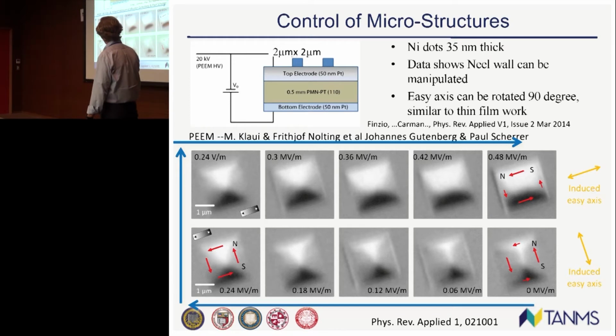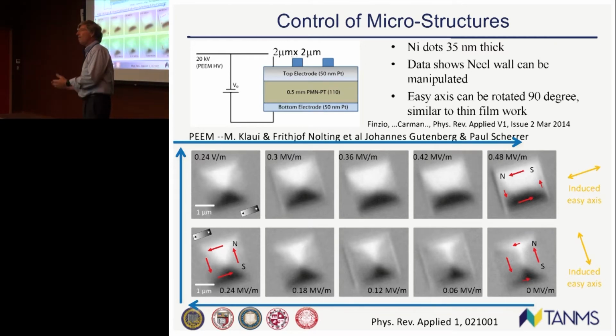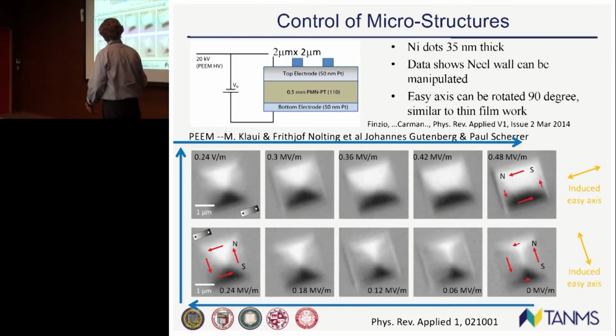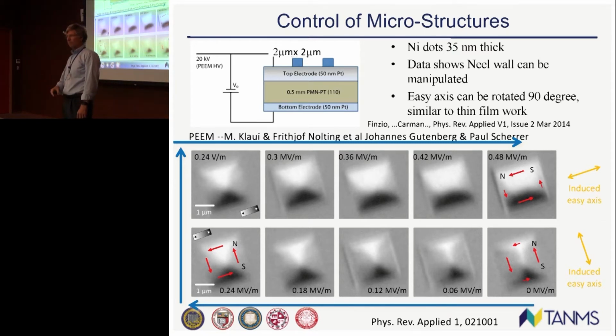Then if we continue to apply electric field from here to here, all of a sudden we see that this white region and black region are considerably larger now. What we've effectively done is what we showed you in the previous slide: we had an easy axis along this direction that now we've rotated by 90 degrees. So now we've effectively achieved our objective.